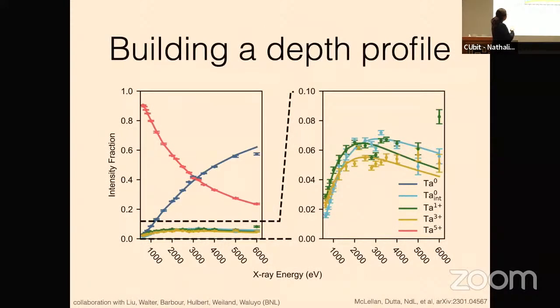So red here is the oxide. You can see that it goes down with energy as advertised, and then the metal goes up with energy. And then there are all of these little interface and suboxide peaks down here. And if you zoom in, you can see that the signal goes up and then goes down, which is what you would expect if they were at an intermediate depth, right?